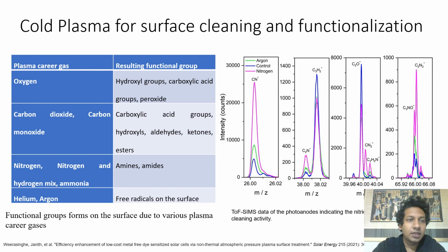This is a time of flight secondary ion mass spectrometry, or TOF-SIMS, comparison of tin oxide films with argon plasma and nitrogen plasma. A significant increase of nitrogen-based fragments was detected on the nitrogen plasma treated samples. Argon plasma exposed samples were also identified with some fragments at lower intensities. Spectral signatures of hydrocarbonated and oxocarbonated ions decreased with the plasma treatment. These results confirm the plasma cleaning effect on the surface.